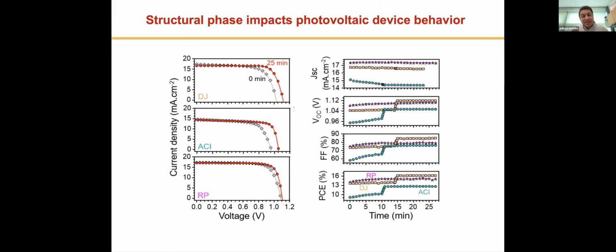So the story starts here, where we were looking at these photovoltaic devices. And what we were actually seeing is changes which look like this. So you take these three classes of the perovskites that I showed you, the Dion-Jacobson, the alternating cation, and the Ruddlesden-Popper. When we put light on this device and we monitor the different figures of merit, like the short circuit current, voltage, the fill factor, what we found is that in the cases where we had the Dion-Jacobson and alternating cation, we were seeing these abrupt jumps in your voltage and your fill factor. And this is something that we did not really understand. This effect did not manifest in the Ruddlesden-Popper phase.